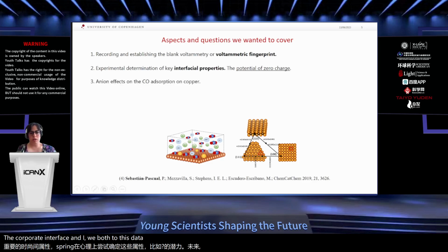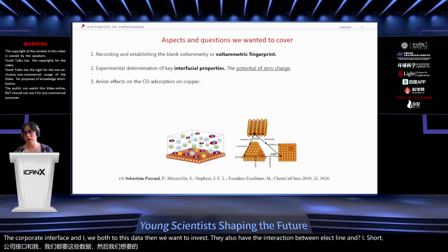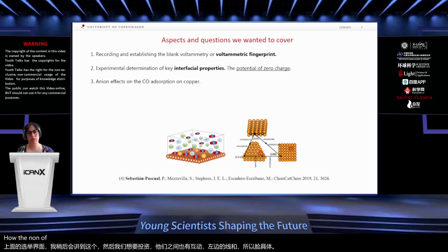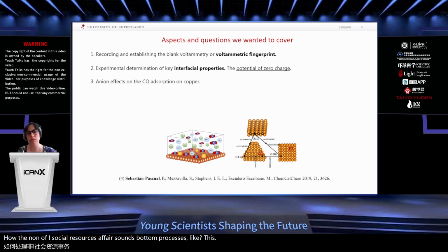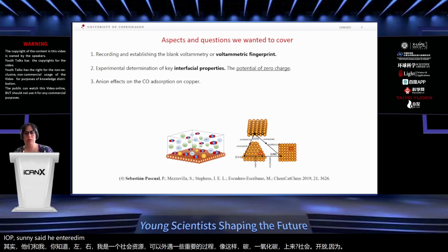Then we also want to investigate the interactions between electrolyte and surface, specifically how anion of the electrolyte, anion adsorption, can affect some important processes like carbon monoxide adsorption on copper, because carbon monoxide is a key intermediate in the CO2 reduction on copper.